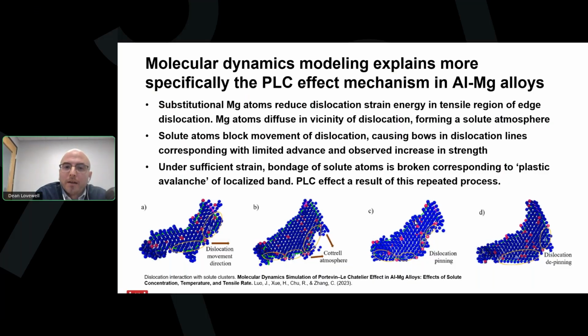Now, while they're pinned, we see the stress rise. And then when they break free, we see what's described as a plastic avalanche of the localized band. At this point, there's a burst in the dislocation movement and the stress suddenly falls. And then again, as this process repeats, this is what we observe and call the Portevin-Le Chatelier effect, more commonly the PLC effect. And again, the reason why we see this in 5000 series alloys is because the magnesium atoms are in solid solution with the metal. And so they're able to travel until they're pinned.